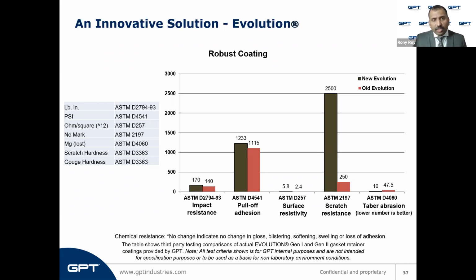And in this test, we run a 2 kilogram load tungsten stylus, which keeps moving up and down till it scratches the coating away and it hits the base metal. And this stylus is connected to a voltage supply. So the moment it touches the bare metal, there is a resistance breakdown. And the 3M coatings, which are good among all the other coatings that are available in the industry, had 99 revolutions of the stylus moving up and down before they broke down.